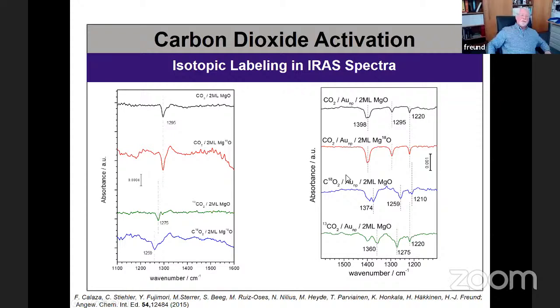Here are the oxalate bands. This one in the middle is the carboxylate, which still remains, but this is the oxalate. And if you change the carbon and the oxygen, and you remember that the oxalate is bound by a carbon-carbon bond, you can understand the changes in the infrared spectrum directly and prove that it is actually oxalate that forms.